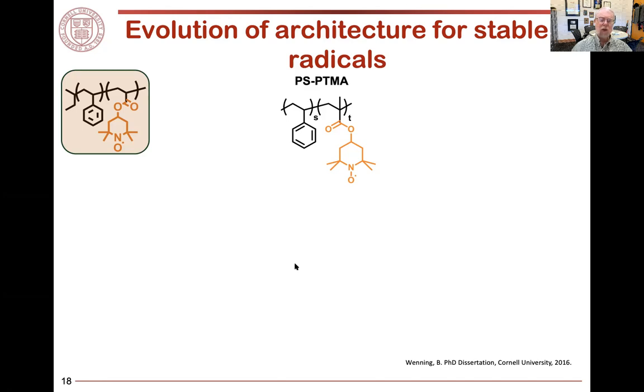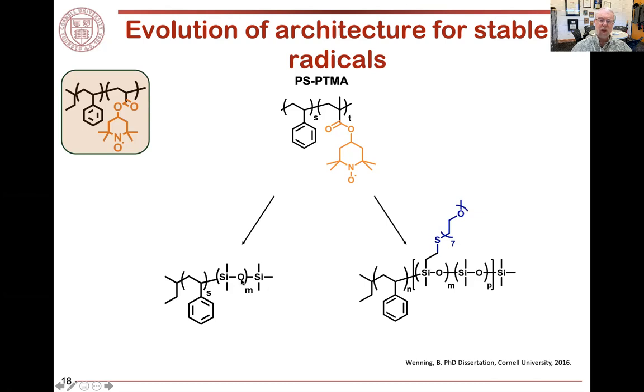Here you see a polystyrene PTMA, the diblock. In our initial study, we had the material, we wanted to incorporate it with our anti-fouling coating. We looked at polystyrene PDMS and polystyrene with PEG modified PDMS. And what we found is that this polystyrene TEMPO methacrylate block copolymer is an awful material. It's brittle, it's rigid, it cracks.